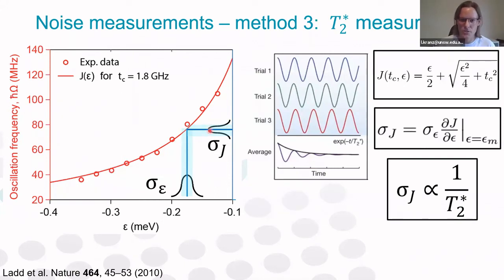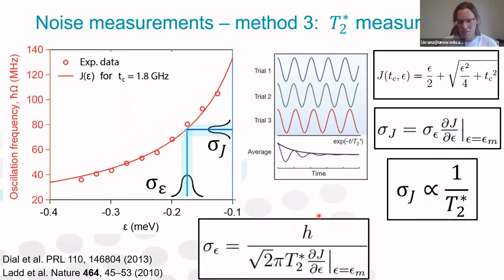Okay, so since you have a distribution of J values, this means that every time you do your exchange pulse, you will actually sample values from this distribution, and every experimental trial, you will get a slightly different oscillation frequency. And if you average all of these trials, you will get dephasing in your oscillations. So this is the standard T2 star procedure. So we would expect T2 star to be inversely proportional to J noise. And all the different things that I just said can be summarized in this master equation that links detuning noise to T2 star and dJ/dε. And this equation and this methodology in general is a standard method to calculate detuning noise in double dot devices.